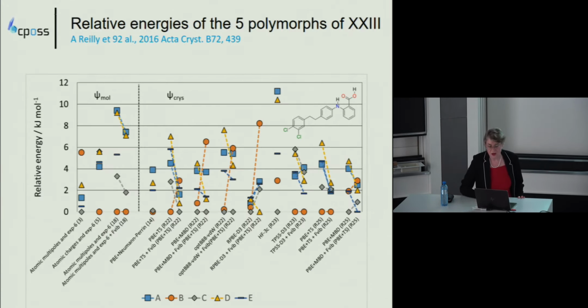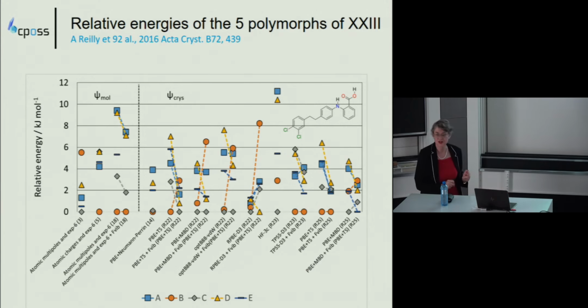One thing we did learn a lot from the system where there were 5 polymorphs, a number of groups developing DFT plus D methods entered by re-ranking sets of structures because they couldn't generate their own. And they then contributed the energies of the polymorphs there. When there's a dotted line, that's that the group did a free energy estimate, usually harmonic phonons, and those were their 2 lists. And that's the relative energy, and you can see from the symbol that the polymorph is sometimes changing which is the most stable.